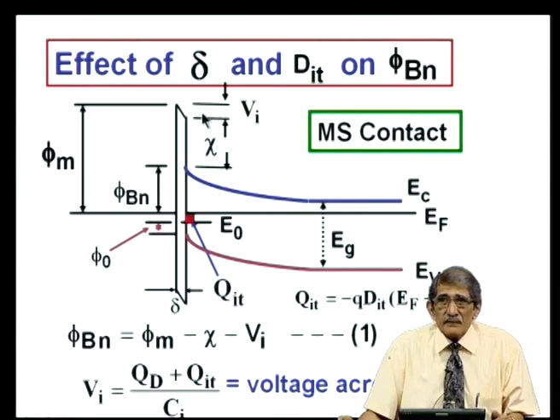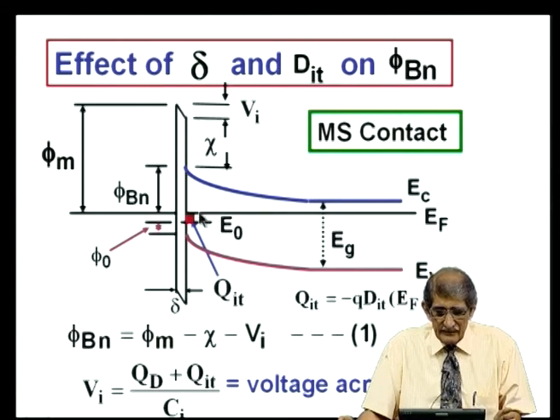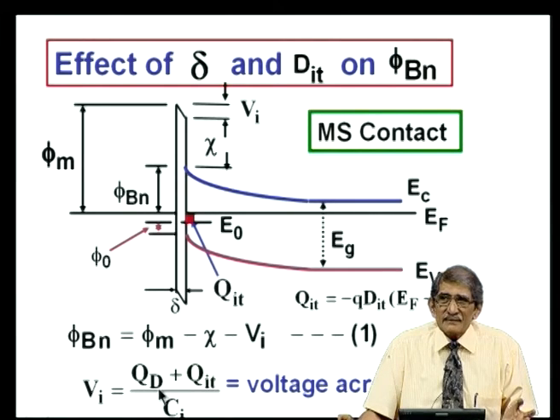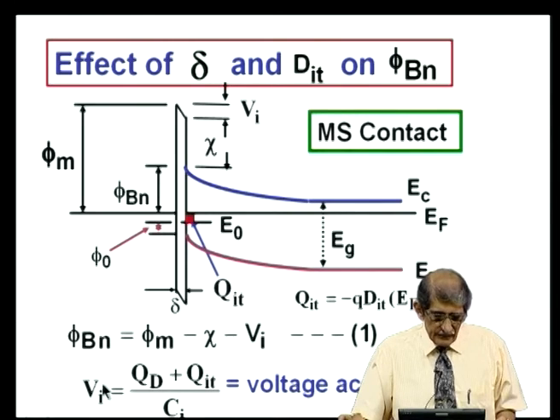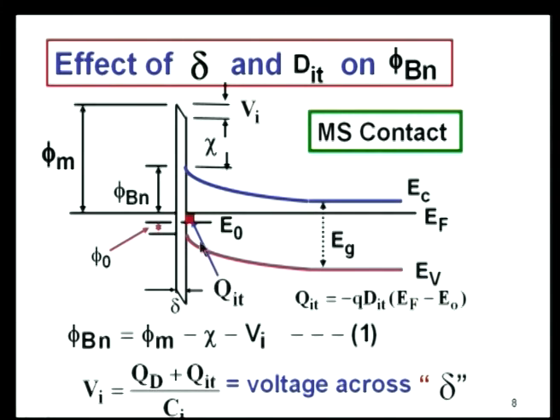So, there is an electric field in this direction from plus to minus here, and there is a voltage drop equal to V_i. What is the voltage drop across the oxide usually? Whatever charge is there beyond the oxide surface divided by C_oxide. In this case, I call it C_i, C interface. So, you have got the voltage drop equal to Q_d, the depletion charge per centimeter square, plus Q_it, whatever charge is present in this red mark that I have shown between the Fermi level and E_0. So, (Q_d plus Q_it) divided by C_i is the voltage drop across the oxide. This may be a small drop, but that affects your barrier height phi_bn. See, when this layer was not there, we said phi_bn is equal to phi_m minus chi. Now, it is phi_m minus V_i minus chi. So, instead of phi_m minus chi, you have got a term V_i which is the drop across oxide. So, phi_bn is that quantity.